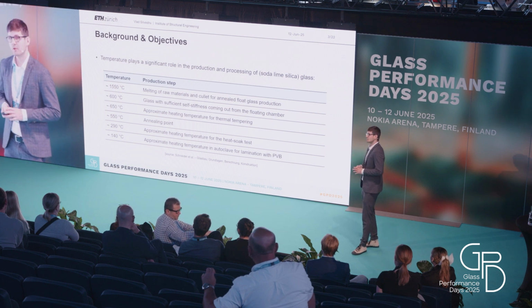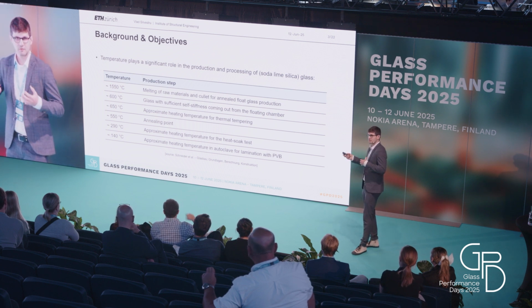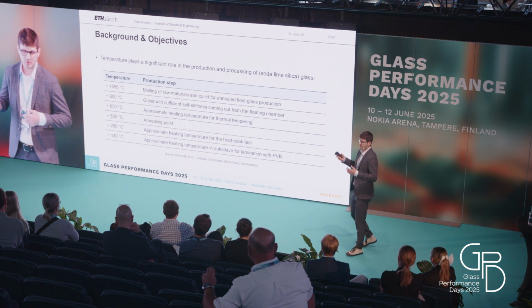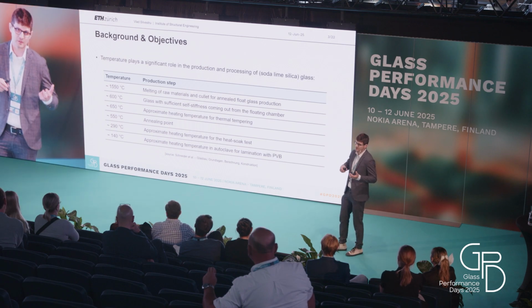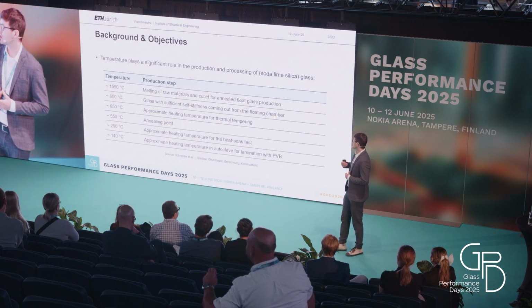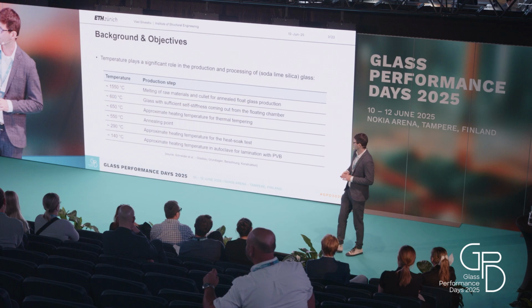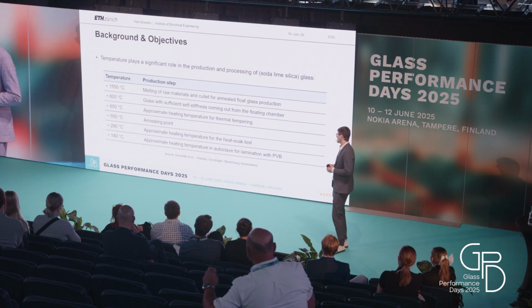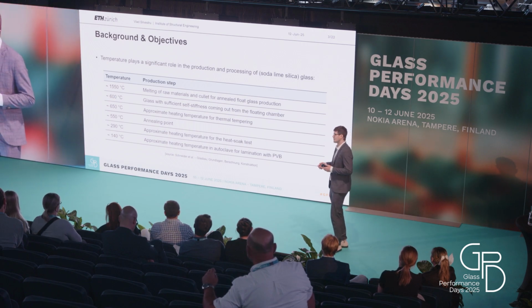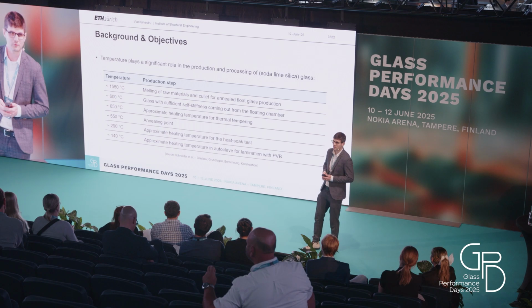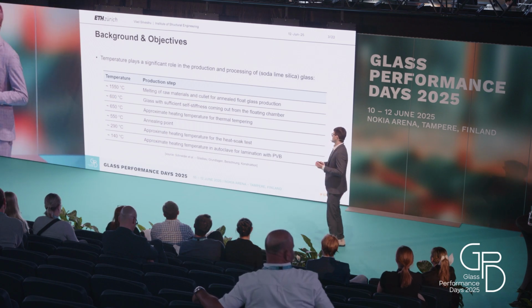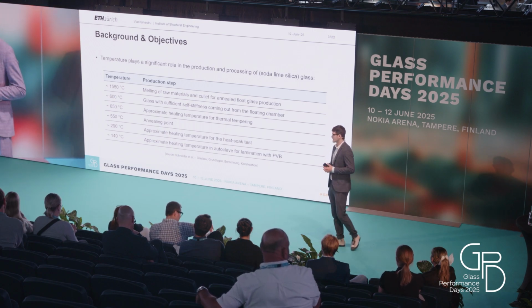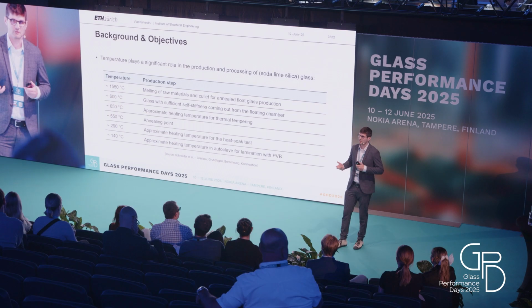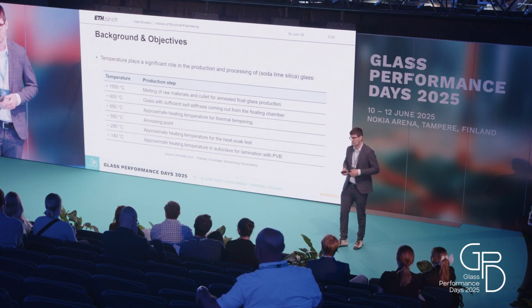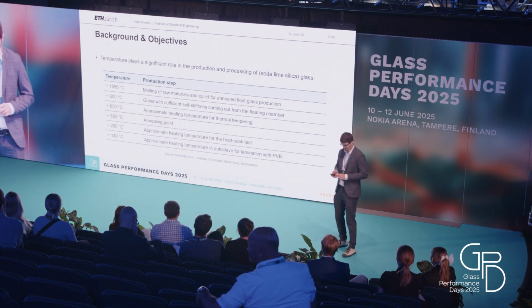The annealing point is quite relevant, especially in the tempering process, but also if we want to reverse this process. What was also relevant for me is the 290 degrees, which is used for commercial heat soak testing for fully tempered glass, since at this temperature it's expected that there is no reduction of the residual stresses, or only an insignificant one, I would say.